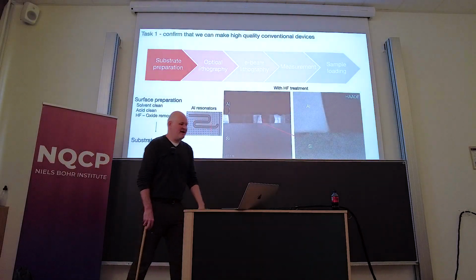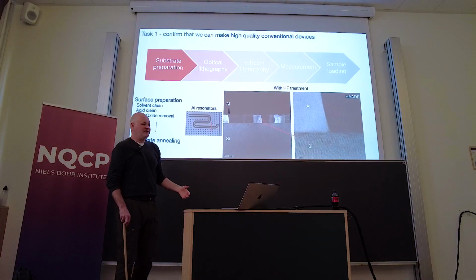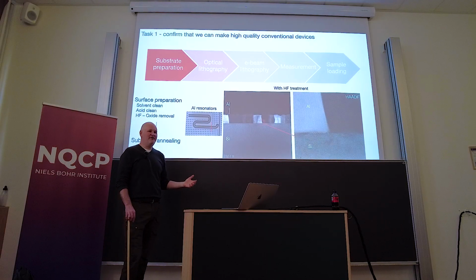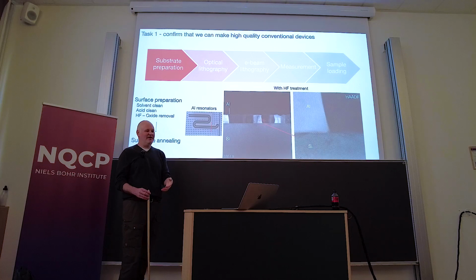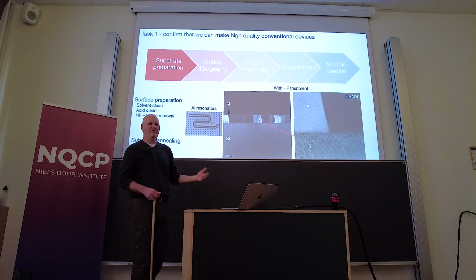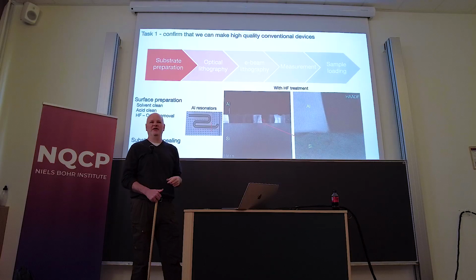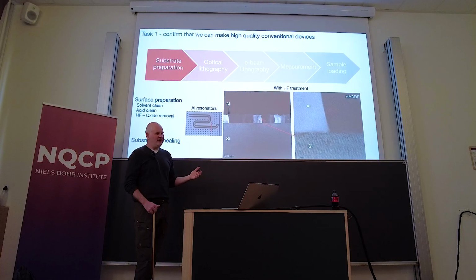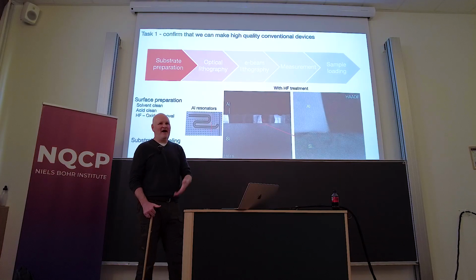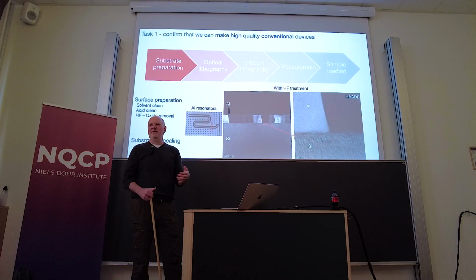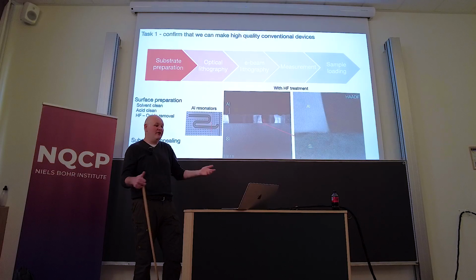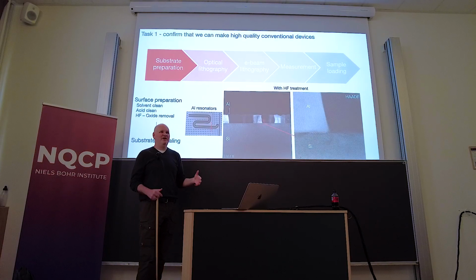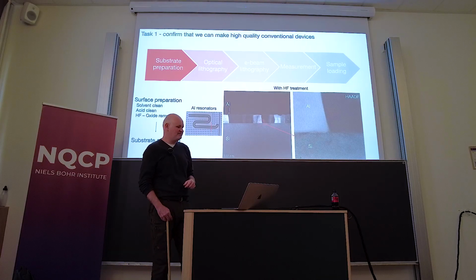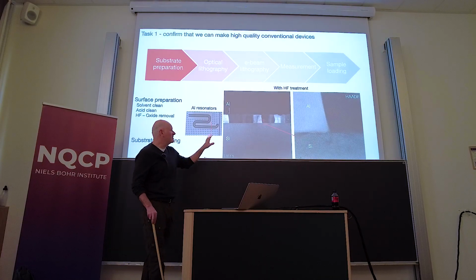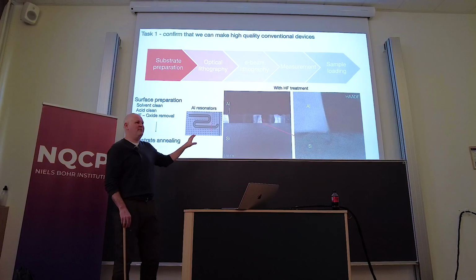And the first thing that we set out to do with this tool was really to, like I said before, make sure that we could fabricate a device that would at least match what other groups can do with aluminum superconducting qubits. Because the problem is we could go immediately and try and build a niobium nitride Josephson junction device, but if the device doesn't work, we don't know if it's because our fabrication is terrible. We don't know why. So we wanted to make sure at least we could make a conventional device that works well. So the first thing we did is we started with making sure that we had good substrate preparation.